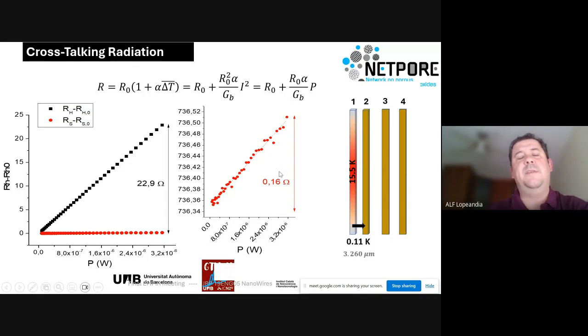Once we have done the first calibration, the first check that we have to take into account is the cross-talking. Not through conduction, because we will complete the experiment in ultra-high vacuum, but the cross-talking by radiation. Because we have a beam around 400 microns long that is around a couple of microns from another beam. And if we do the checking here, we are heating up line one up to 15 Kelvin, which is more than 3 times the temperature rise that we promote in the final experiment. It means we are well over, because radiation will not be linear, in that case it will be cubic.